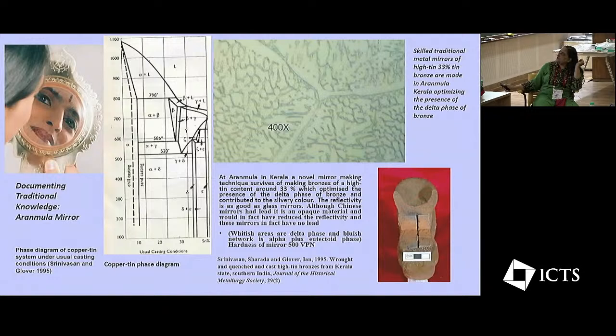And what happens here at this composition is that the bronze consists predominantly of this intermetallic compound, which is delta, which is a compound of a fixed composition of about 32.6% tin. And what is interesting also is that this delta is a very silvery white and hard compound, and that's why when it's polished it takes a very good mirror finish. But it's also something which is formed at a very narrow composition range under usual casting conditions.